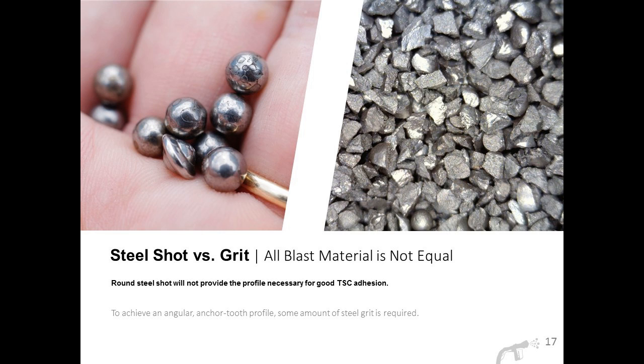What you're seeing on the left is a picture of round steel shot, and this is typically used to prepare a surface for painting, and the surface profile you'll typically get is a peened or dimpled profile, so it's really not that sharp angular profile we're looking for. The picture on the right is depicting some steel grit, and you can tell just by the shape of the grit, it's really sharp and angular. It's got corners of its own that really bite into the steel as it's blasted. So with the right velocity, some mixture of round shot and steel grit is necessary in order to achieve the proper surface profile for metallizing.